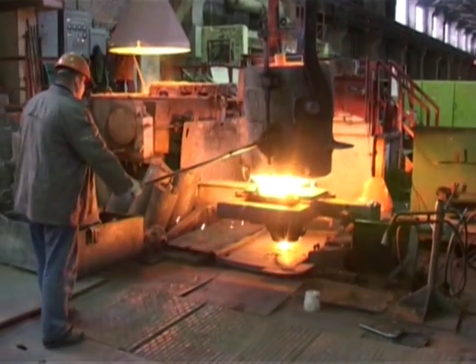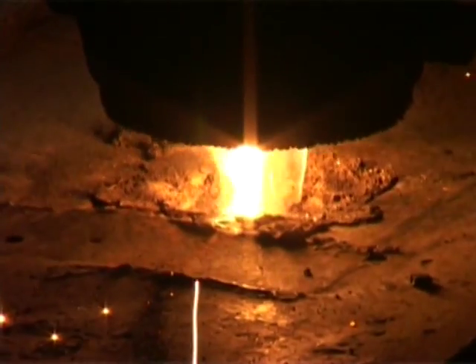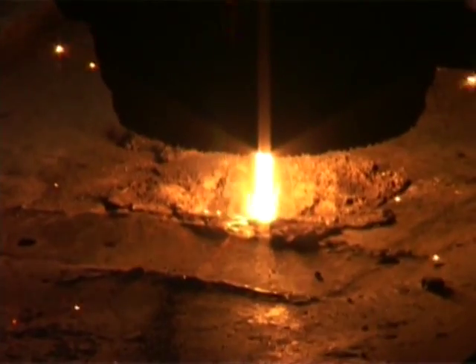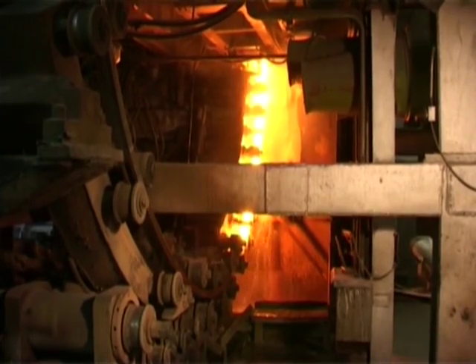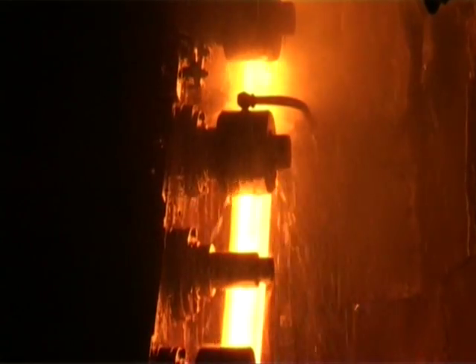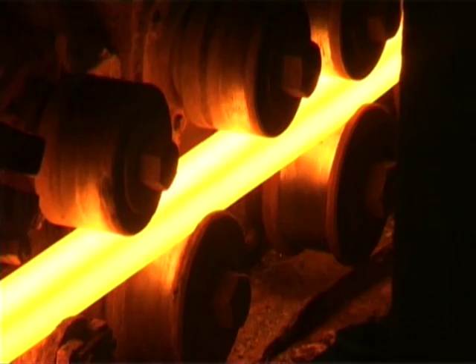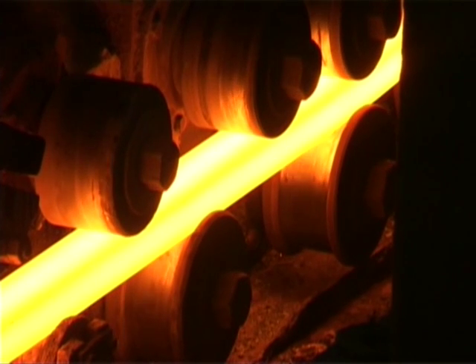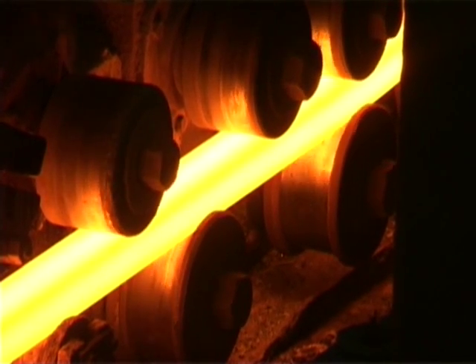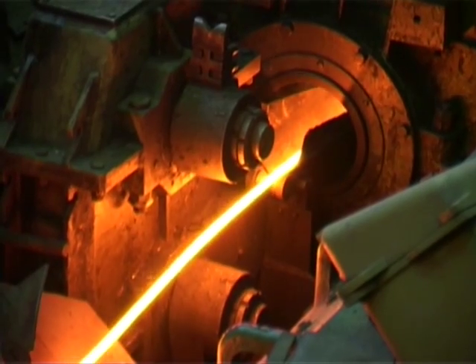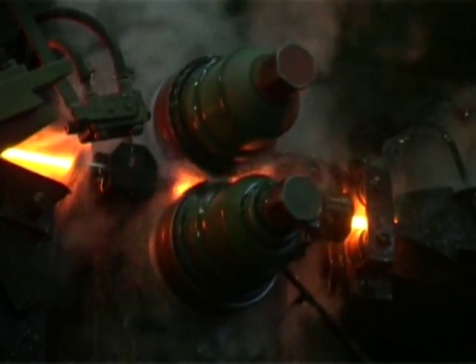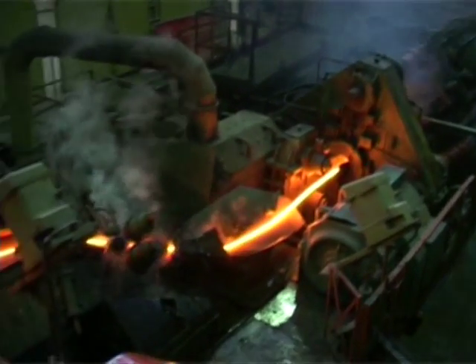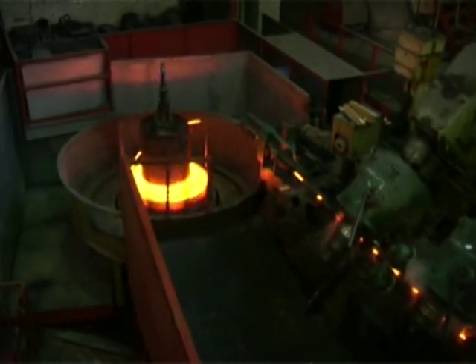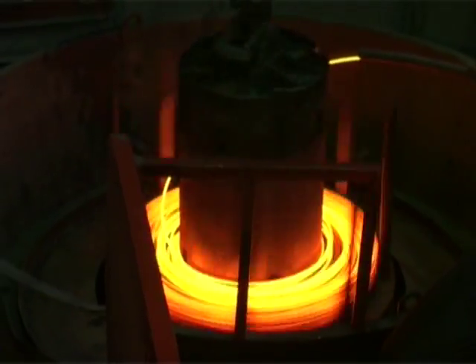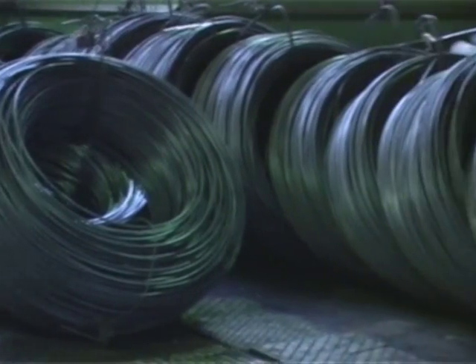The successful cooperation with Metallurgical and Bauman University resulted in putting into effect the idea which for a long time seemed to be impossible. That is to combine in a single efficient and compact module a continuous casting into small sections billets and planetary rolling of sections with high rate pressing in one operation. The use of this technique made it possible to reduce technological cycle, cut power inputs down and increase metal yield when producing wire rod with the diameter of 8-10 mm from a broad range of steels and alloys, including precision ones.